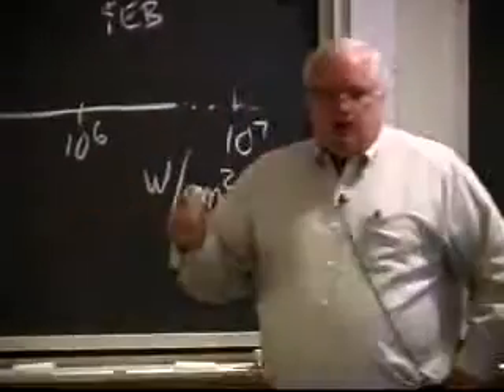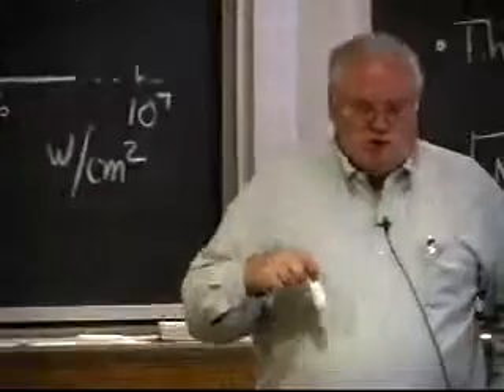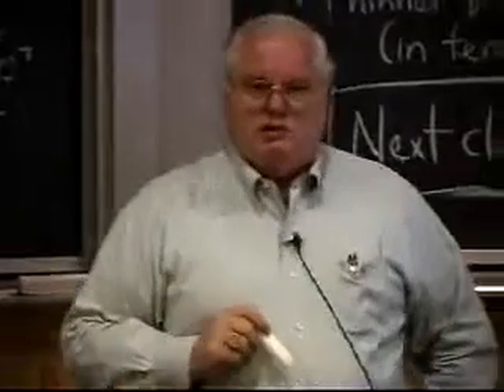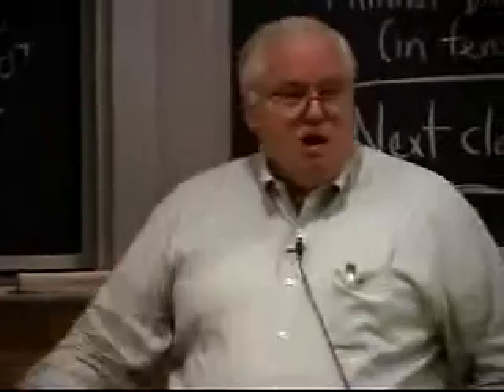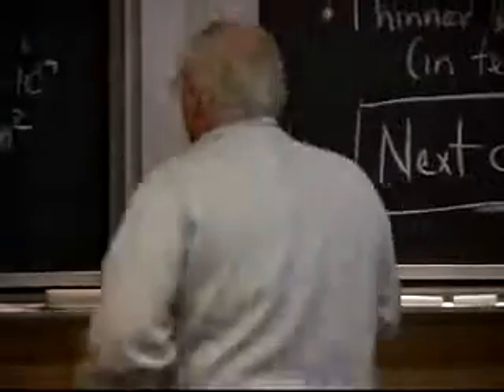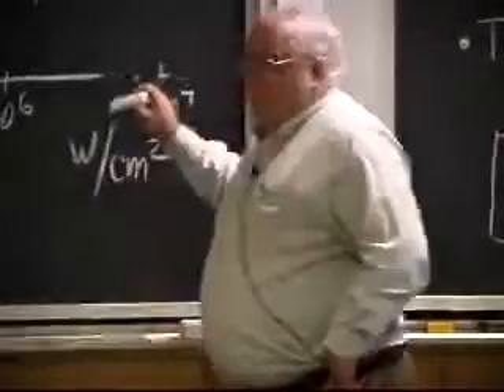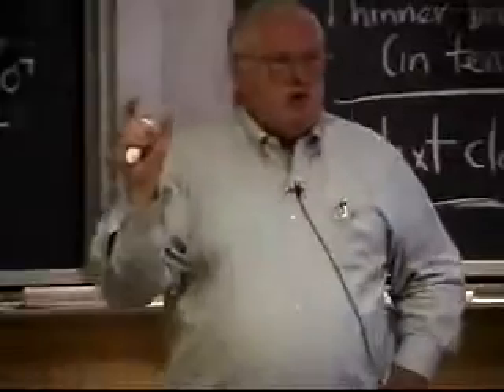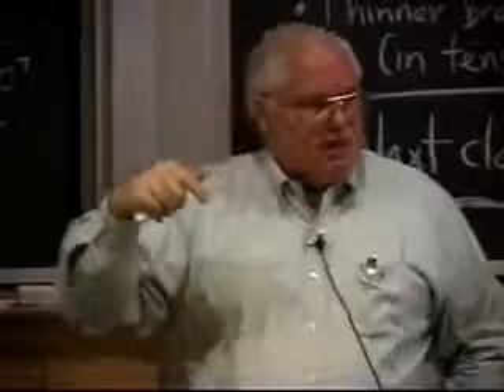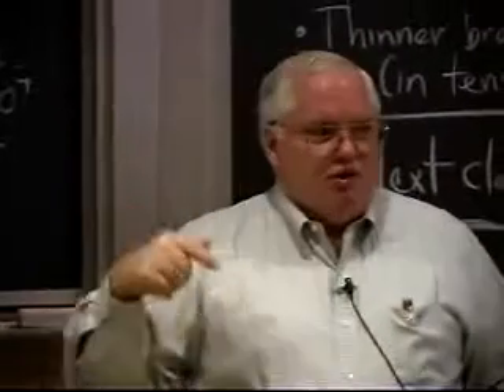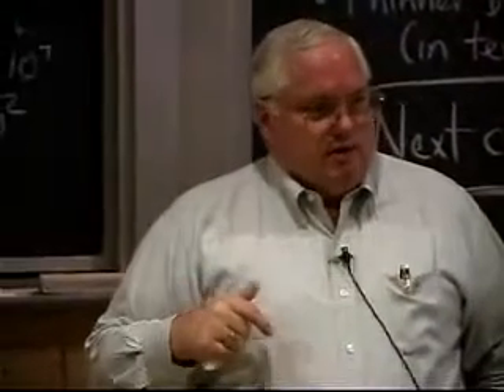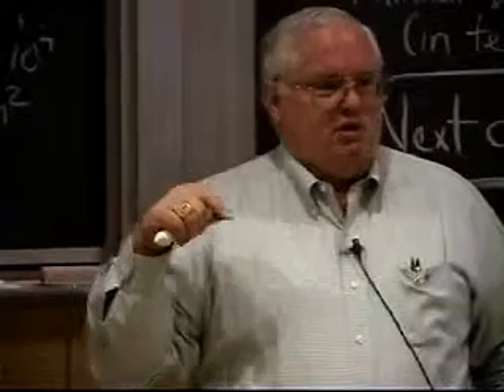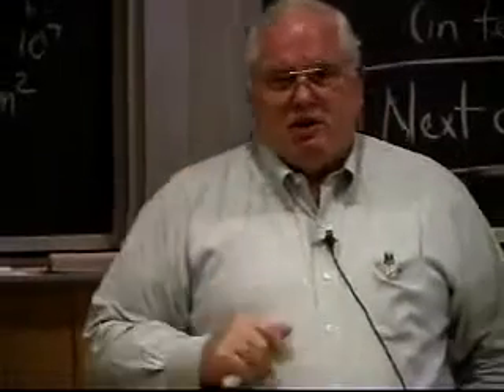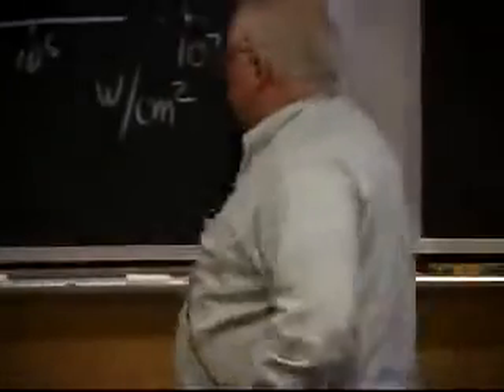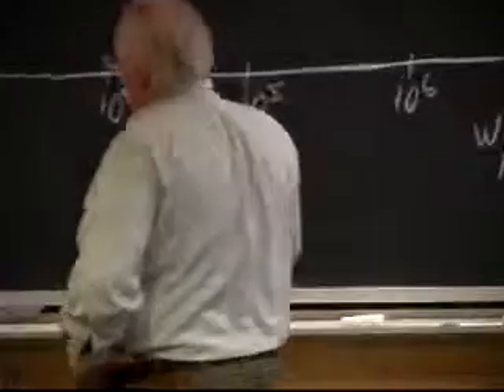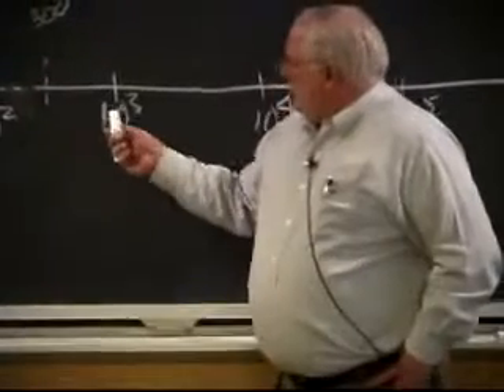But at 10 to the 6th, we'll talk about what it looks like. You can actually start to weld at 10 to the 6th with laser and electron beam. You don't need to go higher. At 10 to the 7th, you drill holes. And I have passed around those turbine blades before with little holes in them for the cooling passages. And those are electron beam and laser hole drilled. And you do that because you're essentially melting the material and blowing it out.